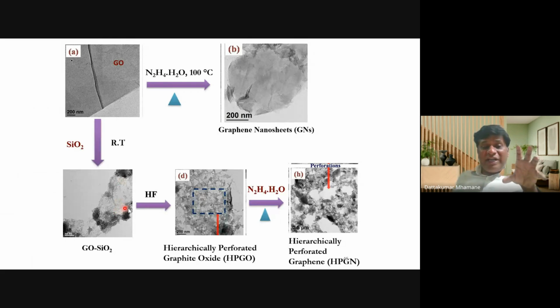So depending on the size of the oxygen containing group, a bunch of silica is getting adsorbed there, chemically attached there. So after HF treatment, that silica is removed with the carbon attached to that particular silica in the form of carbon dioxide. And because of that, we are getting holes, we are getting perforations. So we claimed this first time, and because of that, we got a very interesting paper. So this is graphite oxide. This is not reduced, but it is obtained with holes. And once you reduce with hydrazine hydrate, you are getting perforated graphene like this.